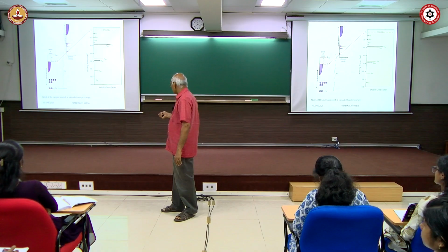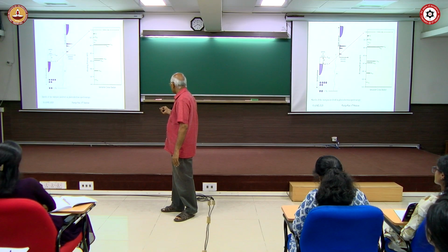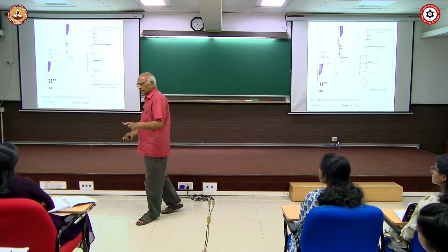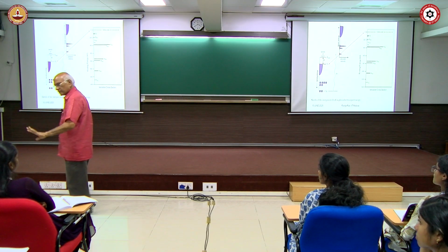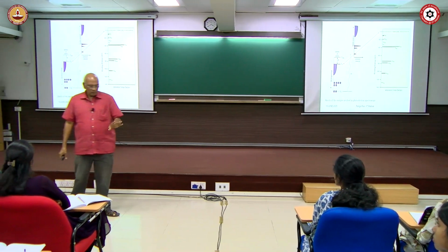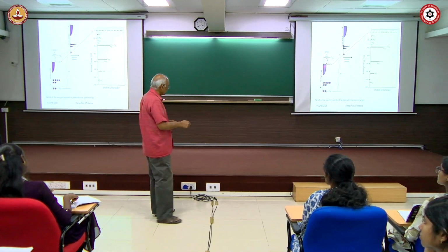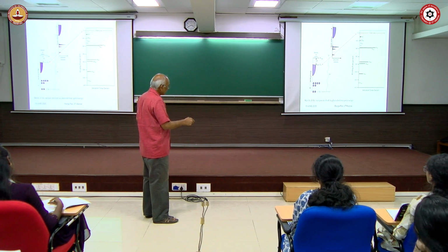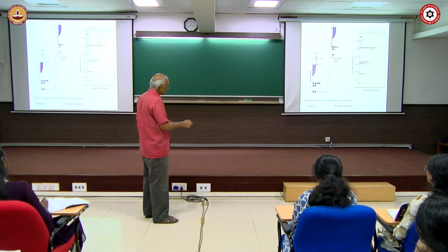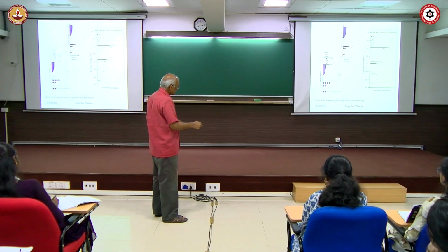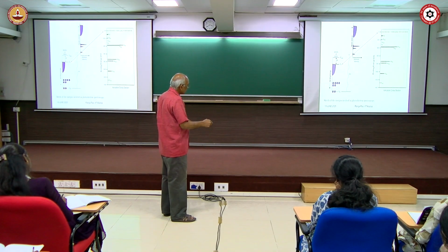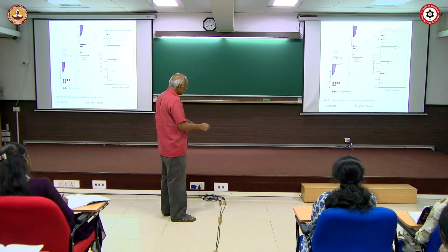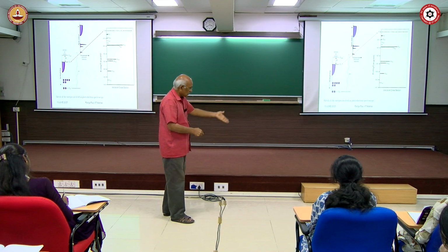Then we have EF. This EF is taken as 0, because we have all those work functions, etc. For every sample, the work function can be measured, right? So normally what people do is this one is taken as 0. That is the Fermi level. From the Fermi level, you start measuring the binding energy. See the binding energy 0, 200, 400, 600. The scale is going down. So you see these 5d orbitals, 5p orbitals, 4f, 4d, 4p, and 3d, 3p, etc.